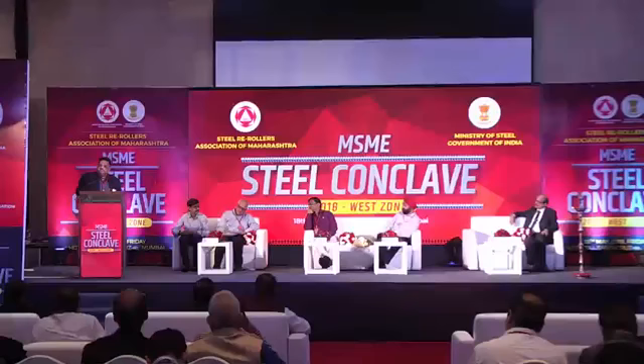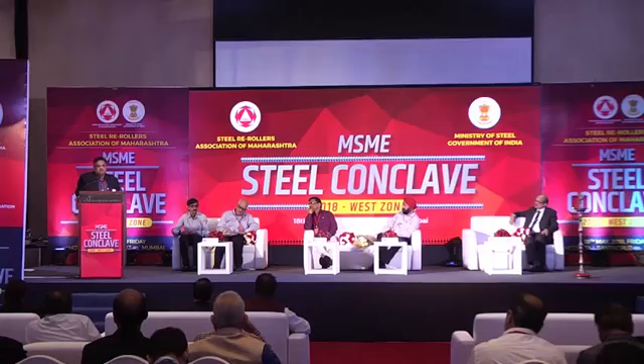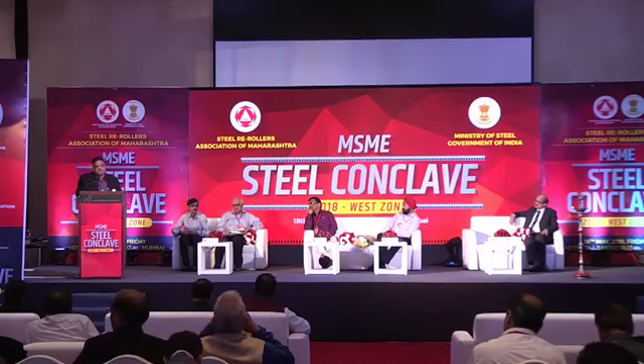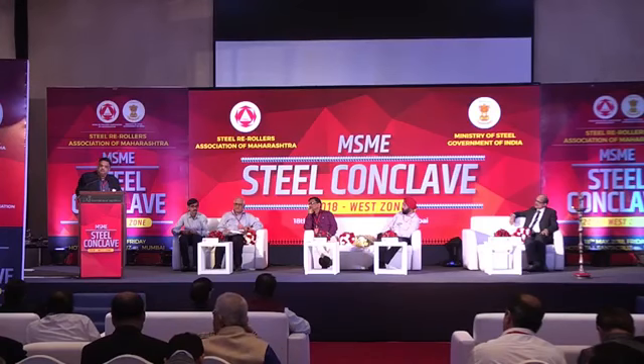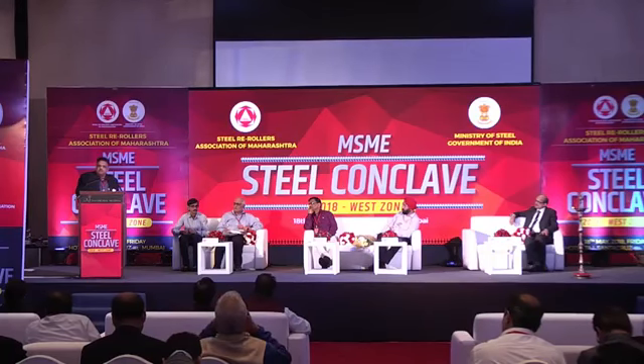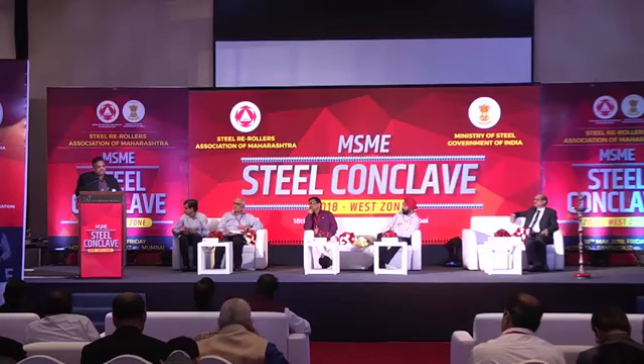Having said that, we believe that there will be a short-term mismatch between demand and supply. Any capacity which primary producers, the main producers, create through the blast furnace route, especially for the long products, will take a lot of time, and therefore the demand over the next couple of years, at least 2-3 years, will have to be met through the secondary route. And therefore, it is important that the government, the morning session by the Honorable Minister was extremely encouraging, but it is extremely important that this shortage in supplies for the long products, which can happen over the next couple of years till the new capacity by the main producers comes up, will have to be matched by the secondary steel producers.